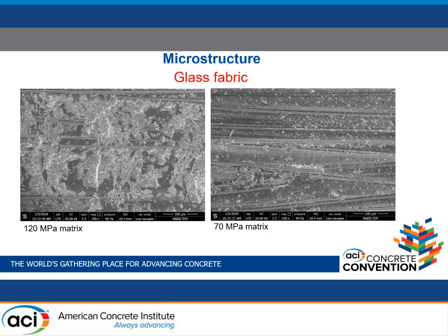This is the microstructure of glass fabric reinforced matrices. On the left-hand side, you see the 120 megapascal matrix, and on the right-hand side, you see the 70 megapascal matrix. This is the scale, 300 micrometer. It's a very focused picture. What we see here is that the dense structure of UHPC creates better bonding with the SPR coating of